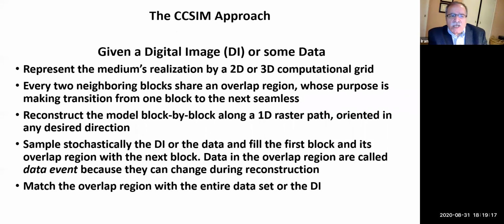Basically, the way it works is that you have some data, let's say a digital image or some data. We represent the model that we want to develop by a computational grid, partitioned into blocks. Then for every 2 neighboring blocks, we also have an overlap region. The overlap region is for having a seamless transition from one block to another. Within each block, we have a distribution of heterogeneities, various structures. And then we build the model block by block by using a raster path and move along that raster path, and it can be oriented in any direction.